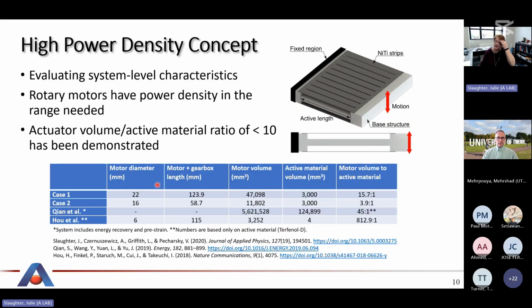And we looked at this concept and said, okay, are we achieving high power density? How is this at the system level? And we did, rotary motors had the power density and the range we needed. So really what I've got here in this table is looking at the motor volume, or whatever the actuator is, to the active material volume. So if you look at competing technologies like magnetocalorics, typically the magnets and all the magnetic components make up about a 3 or 5 to 1 ratio of magnetic material to active material.